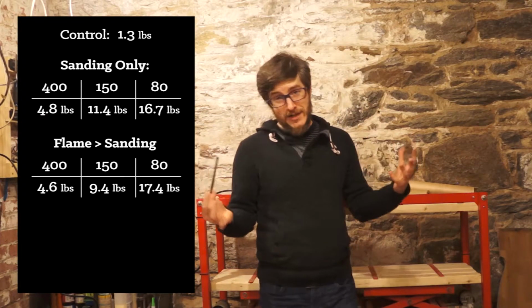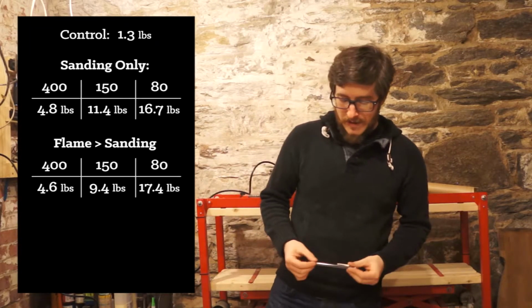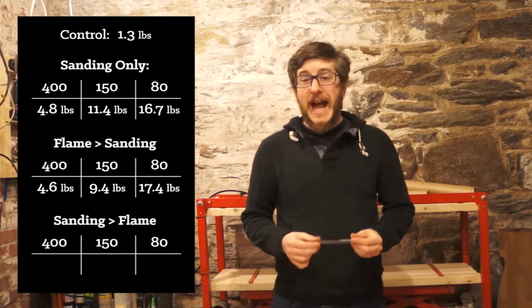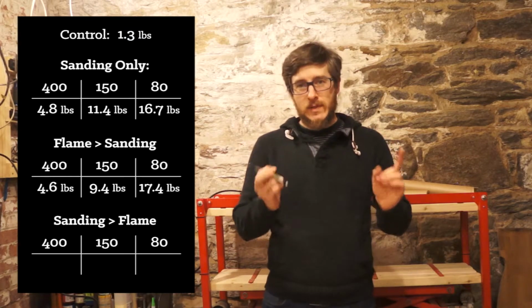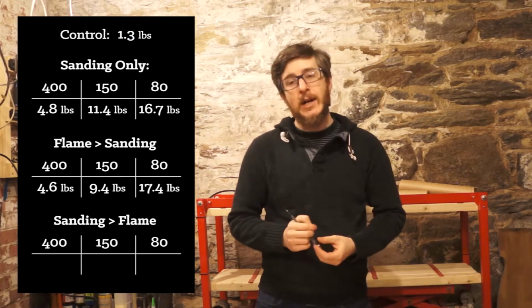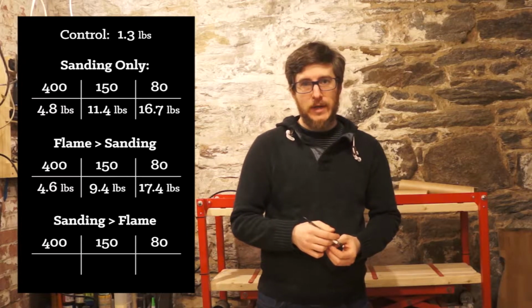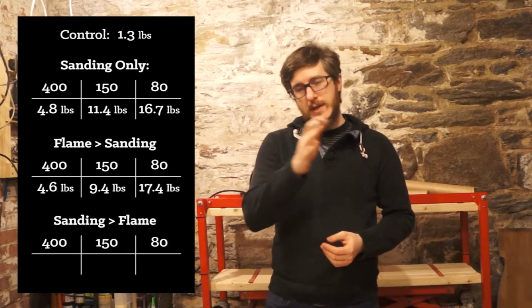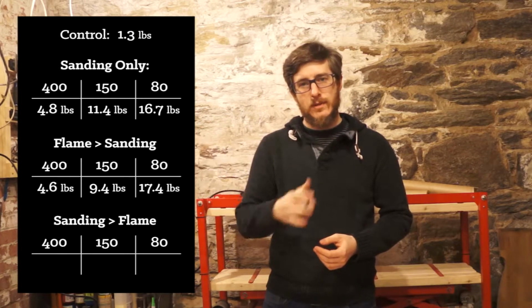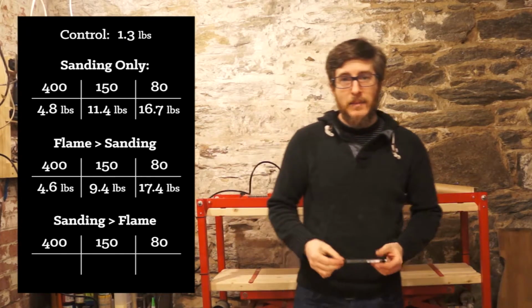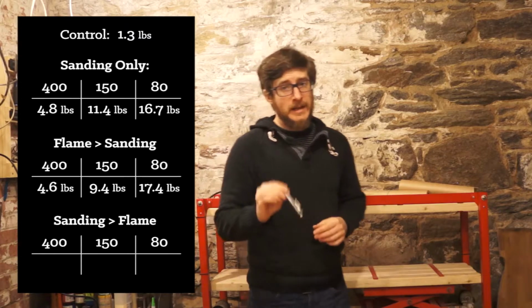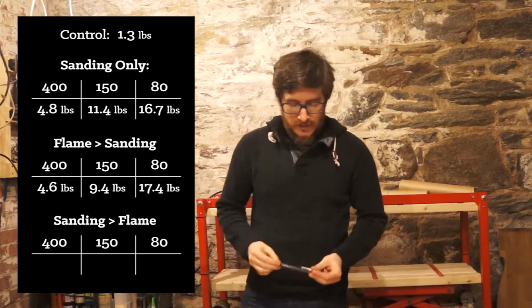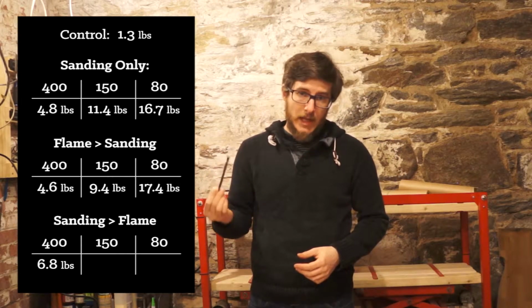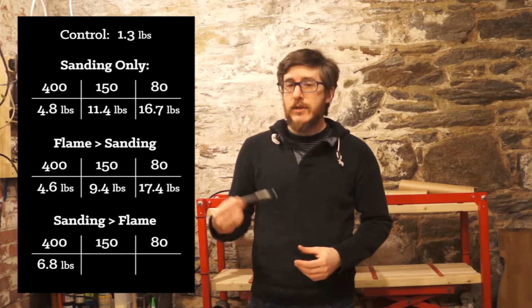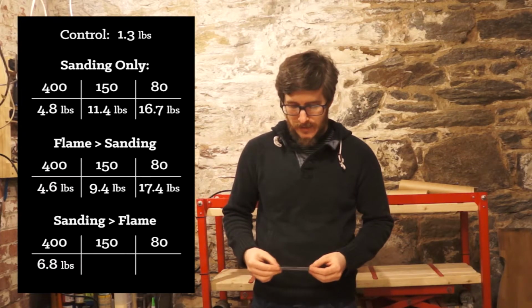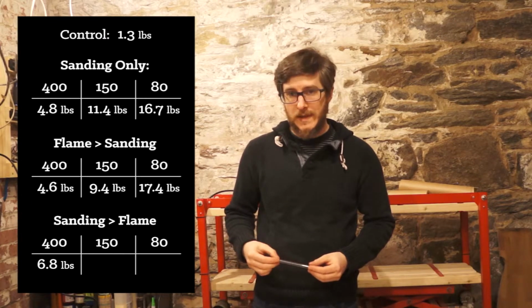Where things started to get really interesting and promising was, of course, the flame treatment after sanding. Once we switched the values that I had written down for the 80 and 400 grit, we still got that increase in value as we went lower in grits. So the more coarse it got, the higher bonding strength it got. But check out the improvement in bonding strength, flame treating after sanding. The 400 grit was 6.8. That's about a third stronger than the other examples, which were coming in somewhere around 4.6, 4.8.